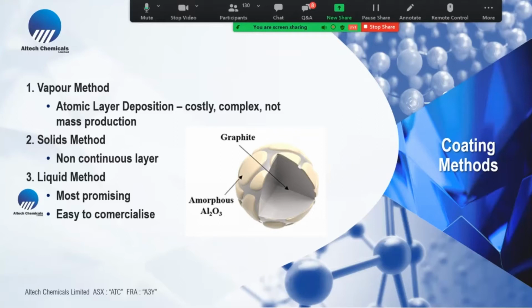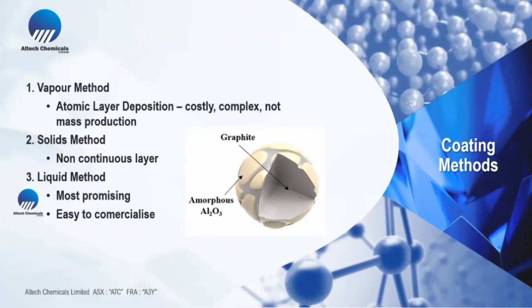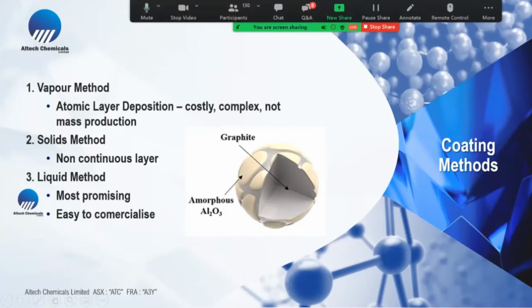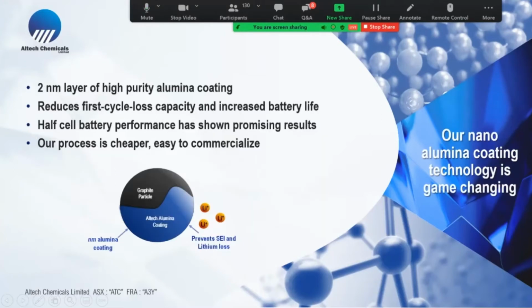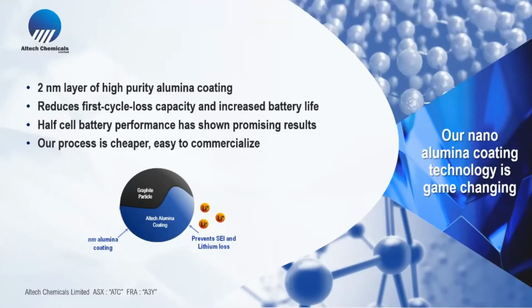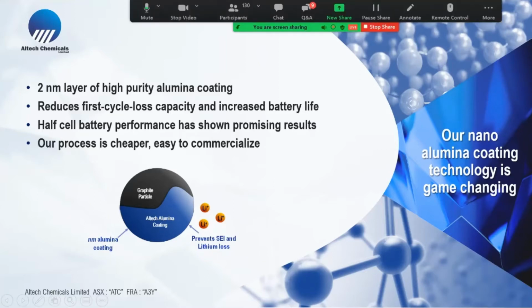Now, there are three ways of coating alumina on graphite: the vapor method, the solid method, and the liquid method. They tend to be quite expensive ways, but essentially our process is a liquid method of coating alumina onto graphite. Now, our 2 nanometer alumina coating is game-changing technology. We can coat the graphite material with a 2 nanometer layer, and that prevents the first cycle loss capacity. Essentially, it pre-coats the graphite and it stops lithium from absorbing onto the first cycle loss or the SEI layer. We've now gone into half cell battery performance tests, and it shows very promising results. So our process is a much cheaper and easier way to commercialize.